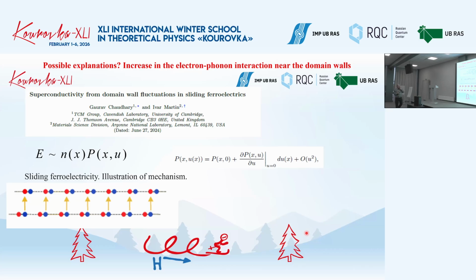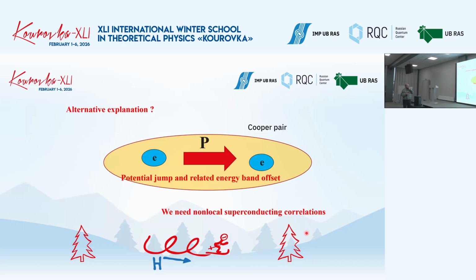And using this argument, these authors assume that, well, it may very well happen that with this domain wall, we can associate some additional electron-phonon interaction, which increases in the presence of domain walls, and this is why we get some additional contribution to the attractive potential between electrons. This was their idea, yeah, but I would try to suggest a little bit alternative explanation, it should be organized as follows.